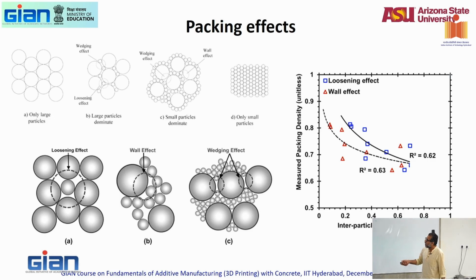So when I have all similar size particles with one particle that's trying to go in, it tries to loosen the system, right? So if you try to put a certain amount of sand into aggregates, it's actually initially loosening it before you start to fill that thing back up. So there's something called the loosening effect where a smaller particle goes in. Again, this is the same thing that happens in crystals when you have defects. It's called interstitial defects. For example, if you make steel from iron and carbon, carbon is a defect that goes into the crystal structure of iron and changes the crystal structure of iron.